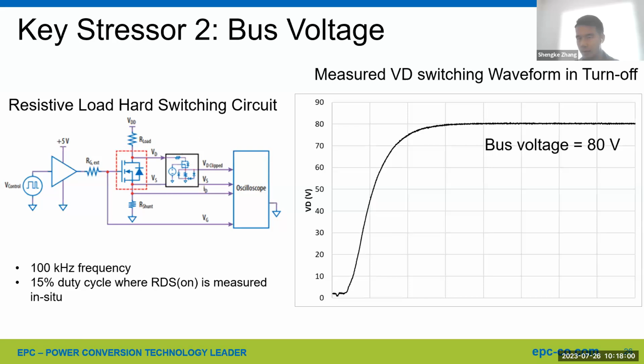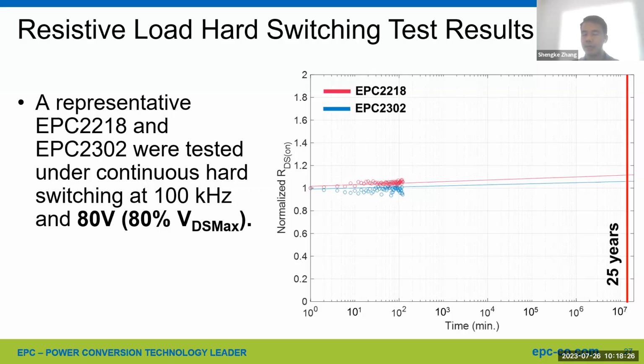So here is the resistive load testing circuit. Here shows the schematic we developed to model the hard switching turn off characteristics, where we can also monitor the evolution of RDS(on) in situ at 100 kilohertz. The drain voltage turn off waveform is shown on the right. So here we tested another representative EPC2218 and EPC2302, both 100-volt rated eGaN transistors. The EPC2218 is the chip scale package part, and the EPC2302 is a QFN packaged device. For both devices we found less than 10% RDS(on) shift over 25 years of continuous operation at 80 volts and 100 kilohertz. This also demonstrates the robustness of our 100-volt eGaN FET under 80-volt off-state bias.